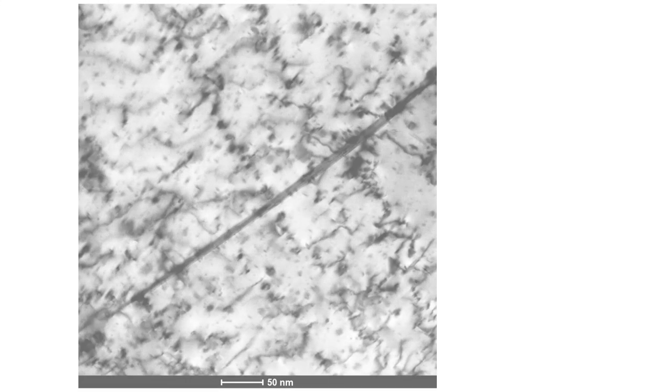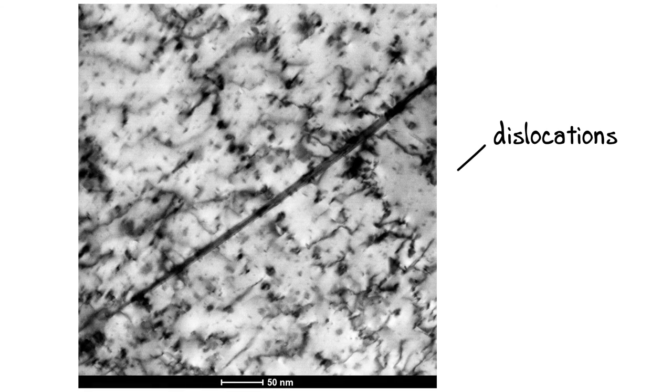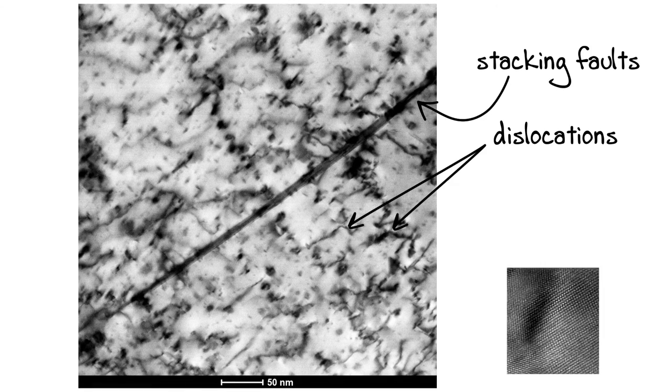We identified lots of local deformation features: plenty of dislocations, stacking faults, local deformation twinning, and so on. A huge amount of energy is stored in the impacted microcubes due to these defects and new, extremely small, misoriented grains.